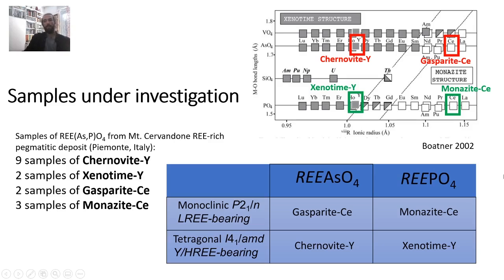All the samples used in this work are natural phosphates and arsenates from the pegmatitic deposit of Mount Cervandone, and they are listed in a table. Gasparite and monazite are respectively the light REE-bearing arsenate and phosphate, sharing the same monoclinic structural type. Also, chernovite and xenotime share the same structural type, in this case a tetragonal one, and they are respectively the arsenate and phosphate of yttrium and heavy REE.